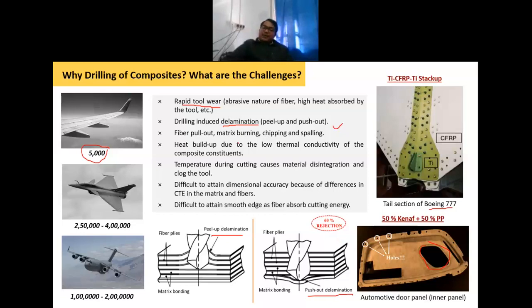Then there are other types of damages like fiber pullout, matrix burning due to high temperature generation, chipping and spalling, other modes of damage. Then heat buildup due to the low thermal conductivity of the composite constituents. So we have the composite constituents like fibers and polymers. If you see the thermal conductivity of both the fibers and polymers, they are quite low.